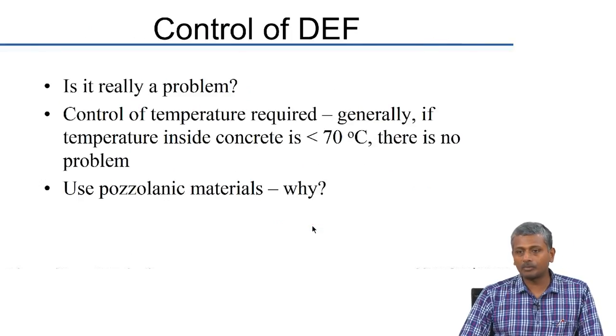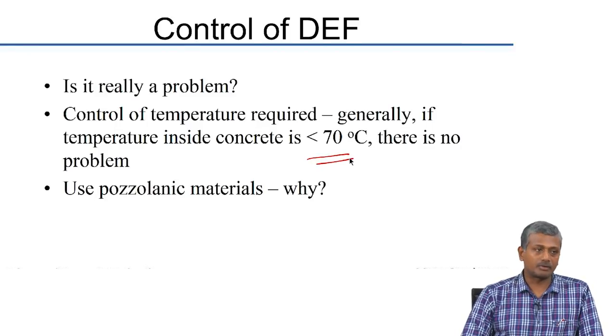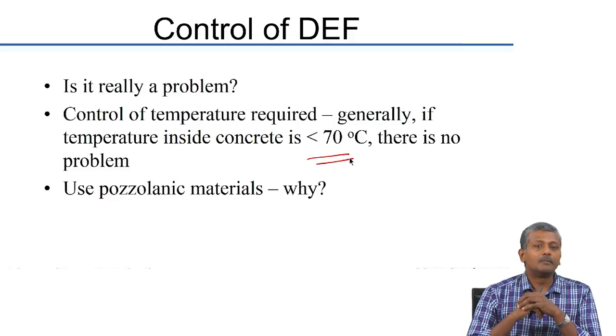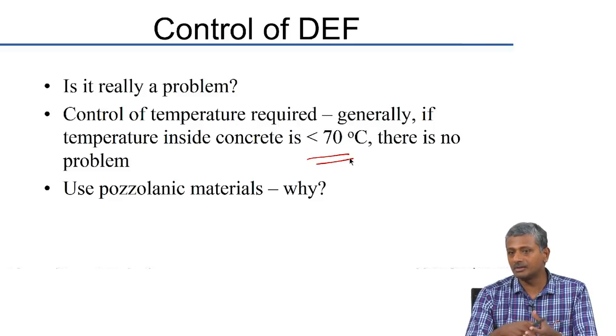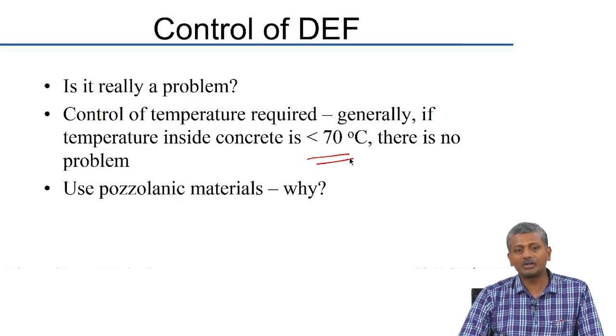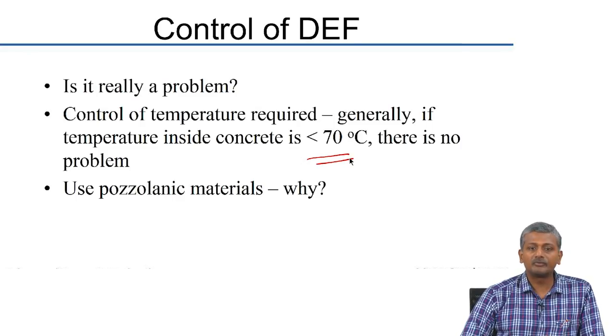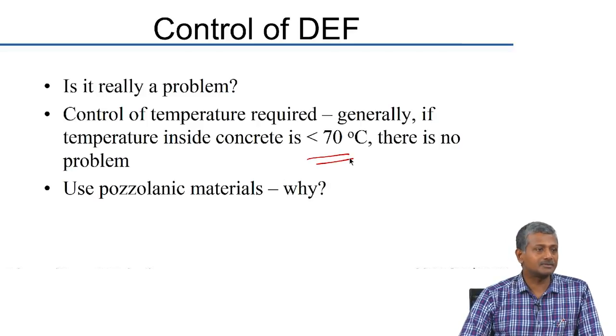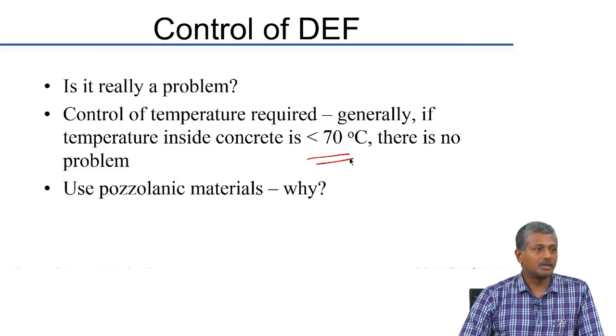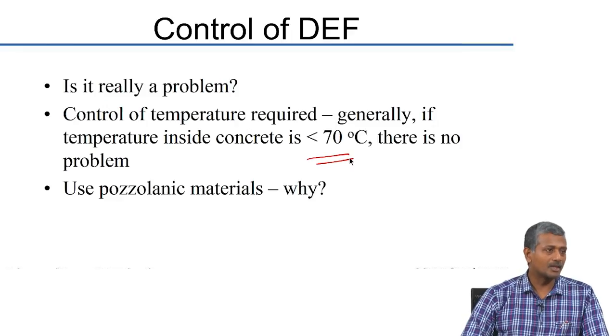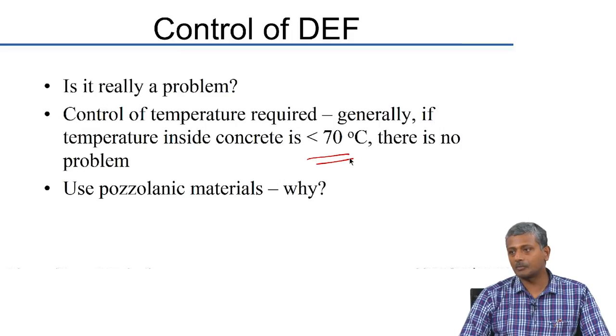DEF is not really a problem as long as you control the temperature to less than 70 degrees in your concrete. The temperature of steam curing can be controlled, but because of very high cement contents in concrete during early hydration, when heat curing is added the internal temperatures may actually rise to much more than 70 degrees. We must be extremely careful when heat-curing concretes, especially high-performance concretes with higher cement contents and lower water-to-cement ratios. However, high-performance concretes also have very little porosity, so not much moisture can enter. If no moisture is available, ettringite expansion will not really happen. So concrete with low water-cement ratio will be resistant to DEF irrespective of the early-stage processes adapted.